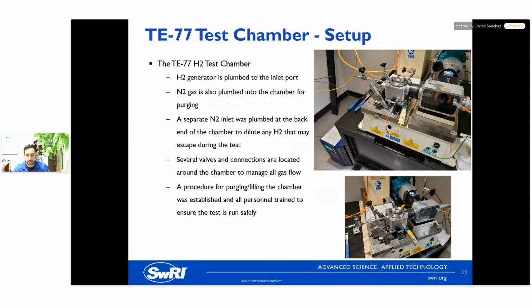So here's more about the actual test setup. The hydrogen generator is plumbed into the inlet port of the chamber. We have nitrogen gas plumbed into the chamber as well for purging, and there's also a separate nitrogen inlet plumbed into the back of the system, in this case the cam box, because if there is going to be any leakage, it's going to be leaking through the cam box side of the T77. That was the most challenging part to seal.